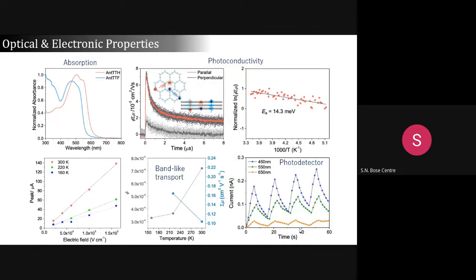Then we tried to understand their optical and electronic properties. From the absorption spectrum, it shows that it has a band gap of almost 2 eV. So if you excite with light, there is a chance to generate an exciton, which eventually will split into free charge carriers. And how these charge carriers are moving, we have tried to probe. We measured the photoconductivity using time-resolved microwave conductivity. And you can see here, after the exciton generation, the free charge carrier is in quite a large amount compared to the previous one. Previously the signal was very faint. In this case, the signal is quite strong.